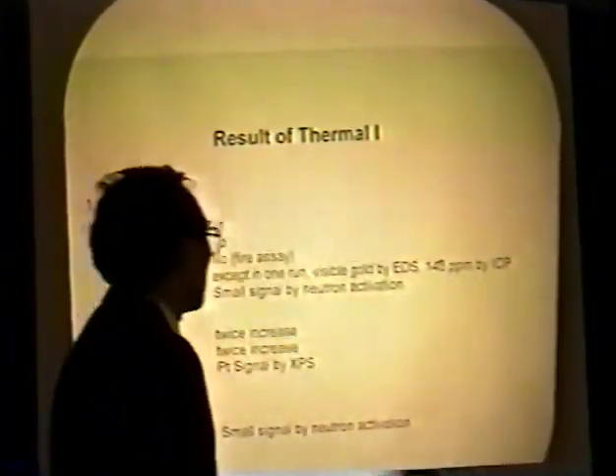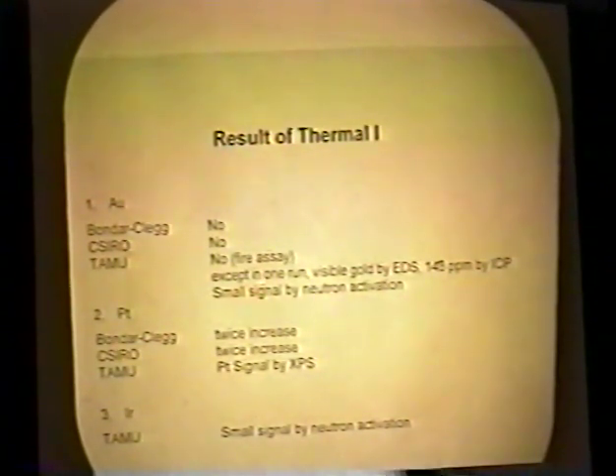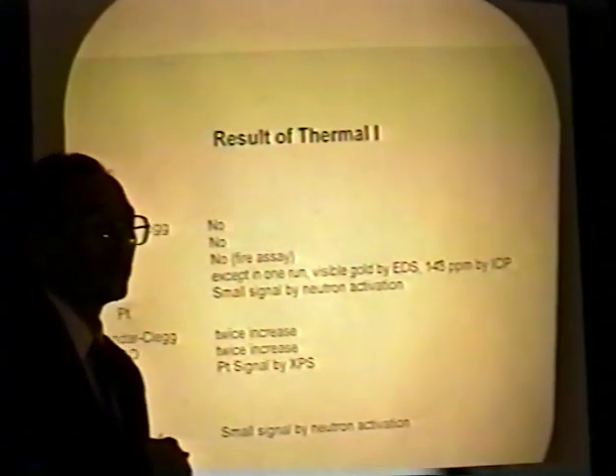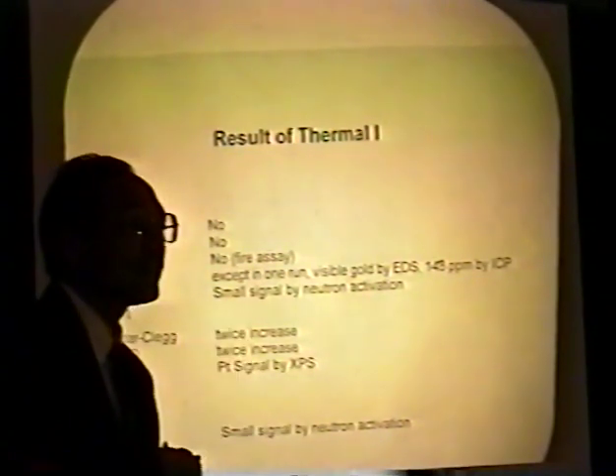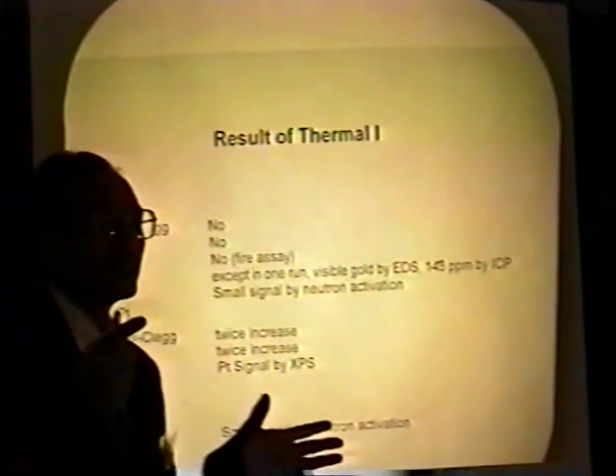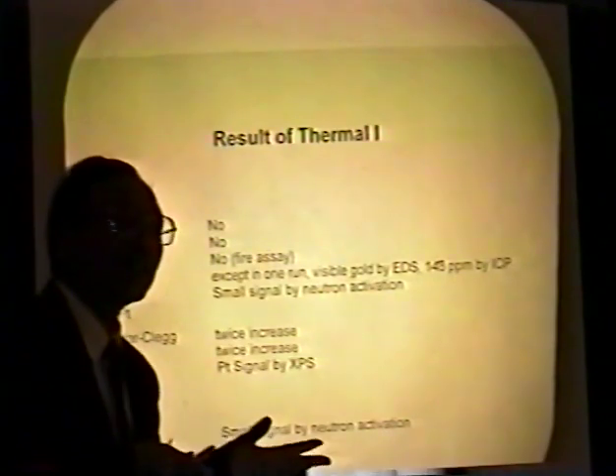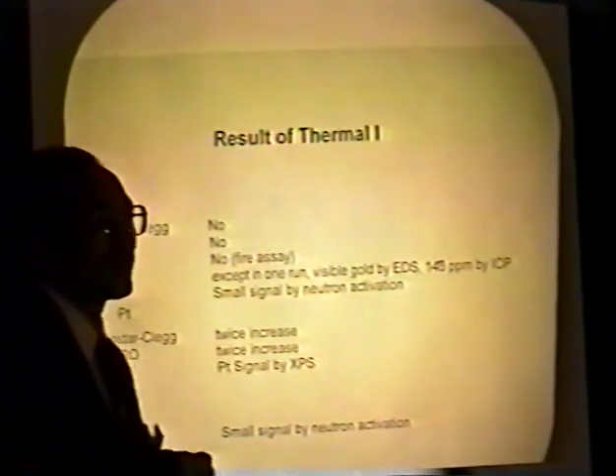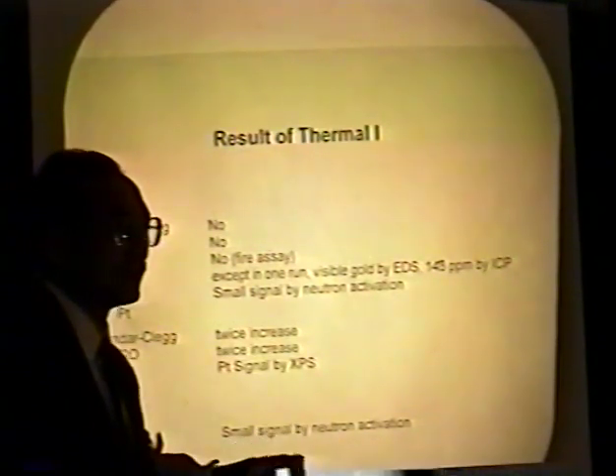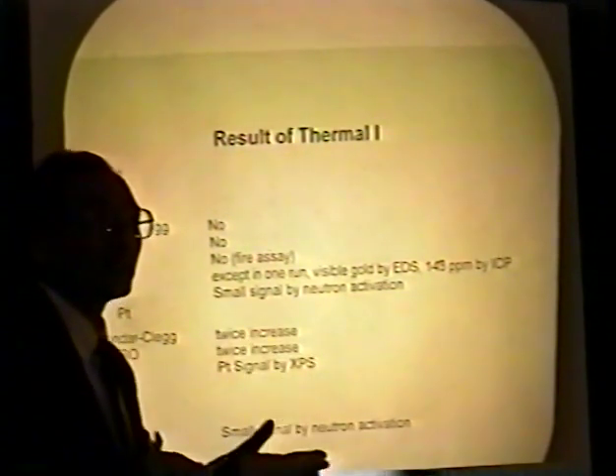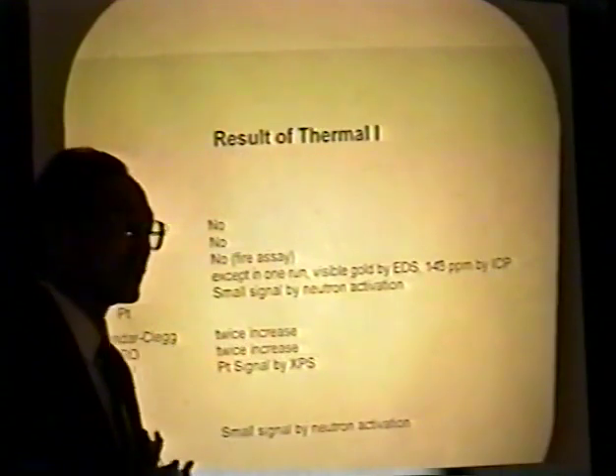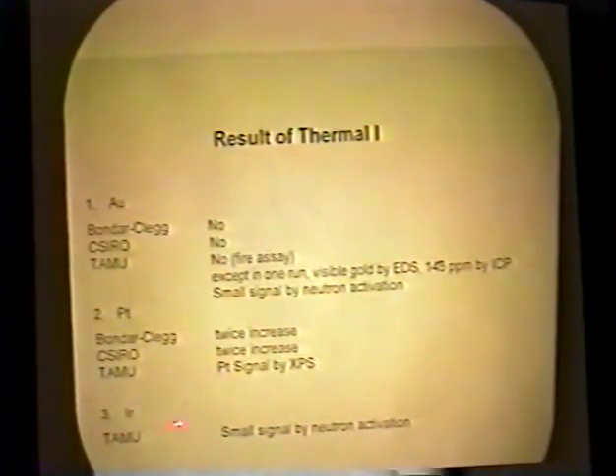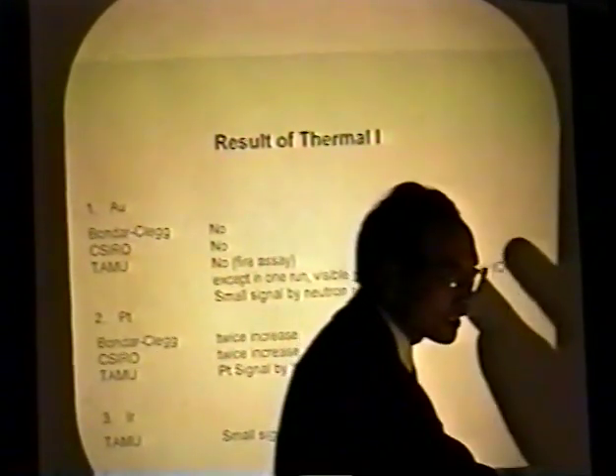Also, when we sent samples to neutron activation analysis, we saw some small signal of gold too. For platinum, Bondar Clegg, CSIRO, and TAMU both got twice the increase of platinum signal. Here we've already counted the concentration factor, because before the reaction it might be 1 kilogram, but after reaction only 500 grams remain. So when I say twice, it means the product concentration is really 4 times larger, but considering the concentration factor of double, we say twice. Iridium signal was also detected by neutron activation. That's the first experiment.